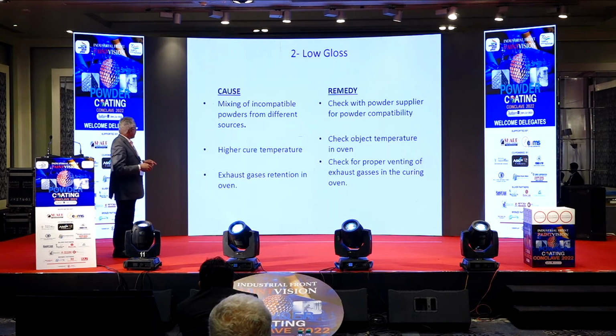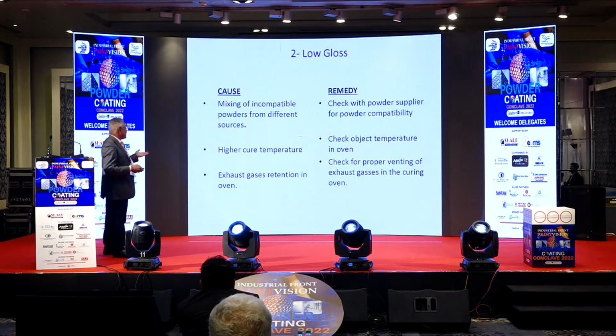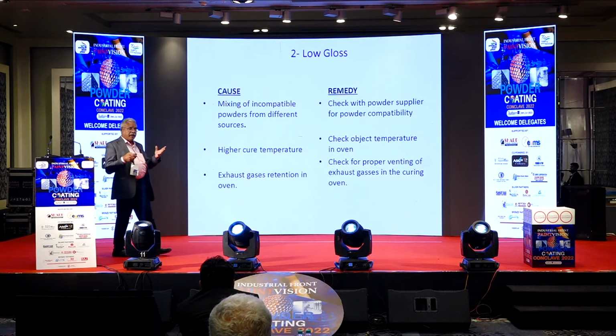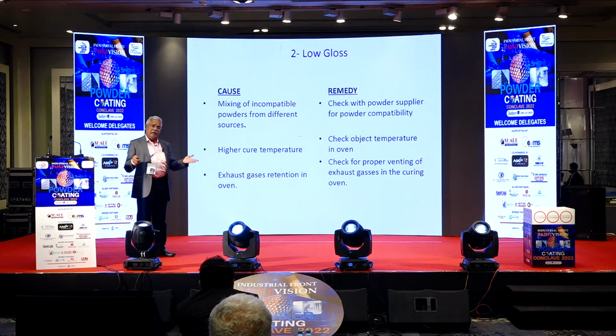That is one reason. High cure temperature: if you cure at a higher temperature than prescribed, you will lose the gloss. Exhaust gas retention: in a gas oven or electric oven, when you heat, gas will be generated. That has to go out. The exit should be proper. Otherwise, this low gloss patch will form.